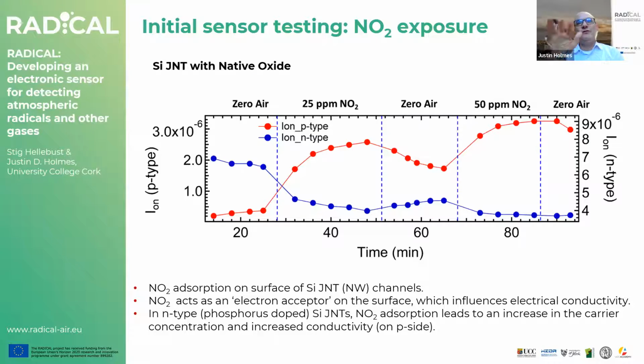So we've got no functional groups here, so we're not looking at selectivity, but we just want to see, can we get a response? Our devices are what we would call the N-type devices, so they're silicon doped with phosphorus. But what happens is NO2 adsorbs on the surface of the junctionless transistor, the nanowire part of the transistor, which is the channel. It accepts electrons from the surface, and it causes a change in the conductivity of the channel.